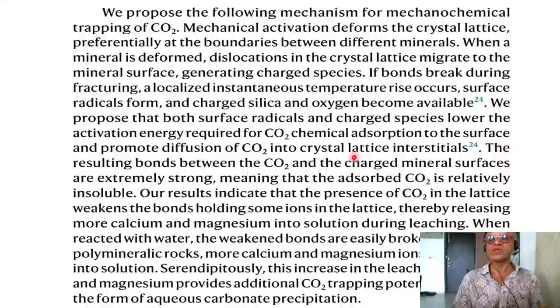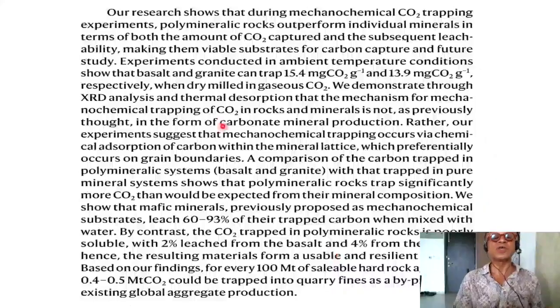Very different than the carbonation process. The resulting bonds between the CO2 and the charged mineral surfaces are extremely strong, meaning that the adsorbed CO2 is relatively insoluble. Our results indicate that the presence of CO2 in the lattice weakens the bonds holding some ions in the lattice, thereby releasing more calcium and magnesium into solution during leaching, the process that happens when the rocks come in contact with water, for example. When reacted with water, the weakened bonds are easily broken. Thus, in the polymineralic rocks, more calcium and magnesium ions are dissolved into solution. Serendipitously, this increase in the leaching of calcium and magnesium provides additional CO2 trapping potential in the form of aqueous carbonate precipitation, kind of a leaching of CO2 into carbonate minerals.